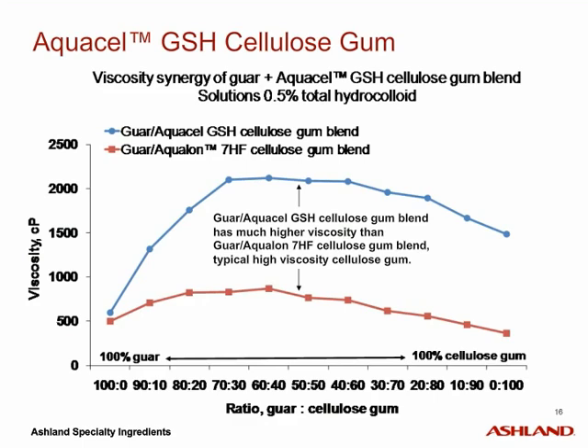Looking at this chart, on the left-hand side are the results for 100% guar gum. The results on the right are 100% cellulose gum. In between along the x-axis are the various ratios that were tested, with the first number being the amount of guar and the second number being the amount of cellulose. This chart clearly shows that the combination of guar gum and Aquacel GSH cellulose gum produces a synergistic viscosity. This viscosity is much higher than what is exhibited by the combination of guar gum and a typical high viscosity cellulose gum grade. In this example, the high viscosity cellulose gum grade that we're comparing against is 7HF.